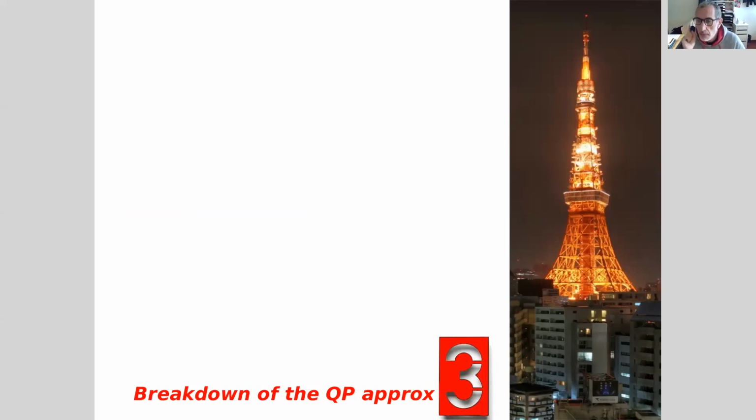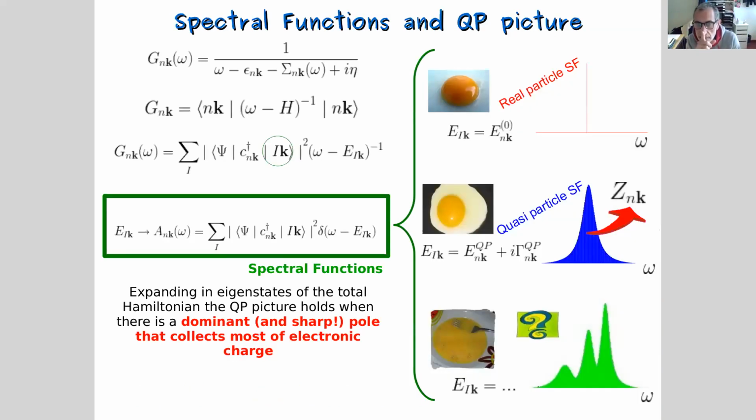So this means that when you do the GW approximation and then you want to produce a quasi-particle approximation, you have to translate all the arguments used in the electronic case to the phonon case. But you have a big problem, because the quasi-particle approximation in the electronic channel is based on the size of the plasma frequency. The plasma frequency in silicon is 20 eV, 21, something like that. So it's large. Because of that, when I plug this in the self-energy, the self-energy gets those peaks very far from the gap, and in the gap I just see a very smooth object. Actually, with phonons this is not true anymore, in the sense that phonons can produce peaks in the self-energy very near the gap, with a super tiny frequency. So this means that it can eventually break the quasi-particle picture.